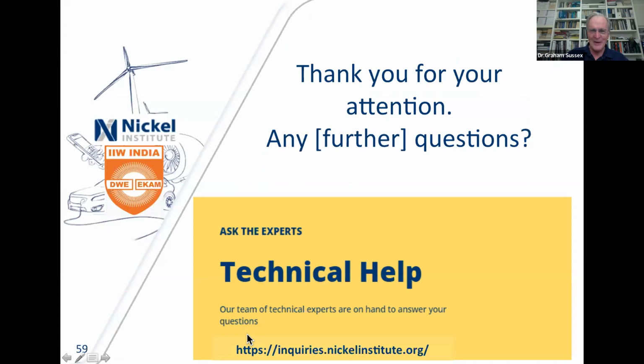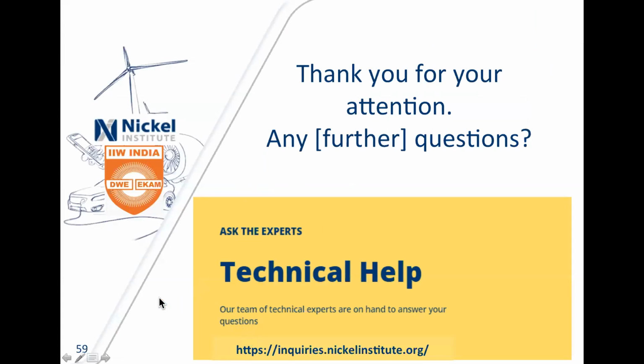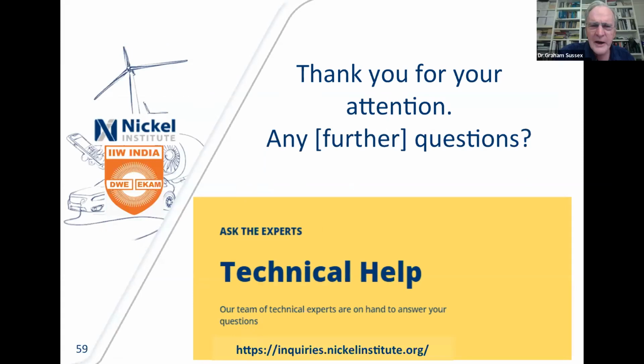Now, what were the questions? Yeah, Graham, there are a few questions in the Q&A. If three different metals are in contact, carbon steel, aluminium, and stainless steel, which one will corrode and why? Well, the one that is most anodic will corrode. That's not quite so simple though, because it's not only the potential that matters, but also whether it forms stable oxides. So if you put these three together, the carbon steel will corrode because it's not got any protection at all. The aluminium will corrode less, but it may pit. And the stainless steel basically has a passive film on the surface and it'll sit there. And actually it will drive the corrosion of both the other two.